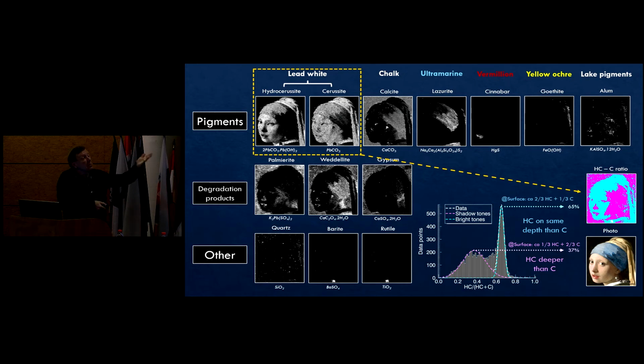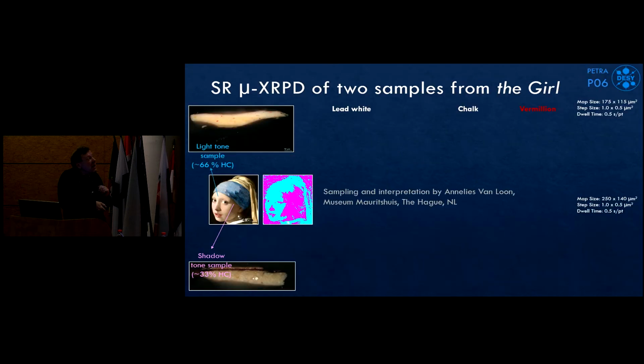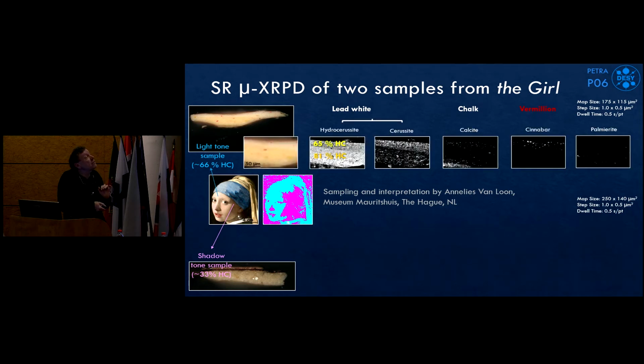And so a small miracle then happened, you could say. We told that to the conservators, and they agreed to sample where things should be sampled to get a view on these two layers. This took some convincing and also searching for positions on the painting where there was already damage, but they did do that, and we did analyze them at Petra, P06.